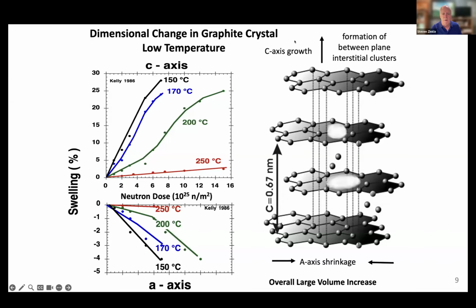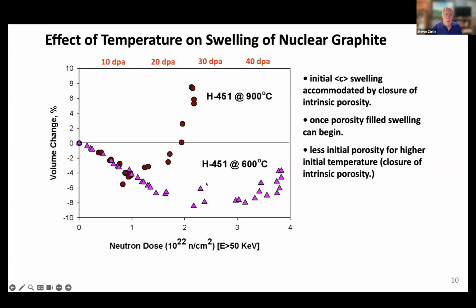And so in the case of graphite that's been heavily studied, at low temperatures, you can see very pronounced swelling in the C direction of the hexagonal close pack structure, and moderate dilatation in the A-axis direction of that material. And so this differential lattice swelling can introduce tremendous stresses at the grain boundaries of the material. If you go to higher temperatures, there's a tendency for an initial sintering of the material of a few percent, and then there's a turnaround, and then it goes into a rapidly swelling regime. The higher the temperature, the shorter the duration until it goes into this high swelling regime.